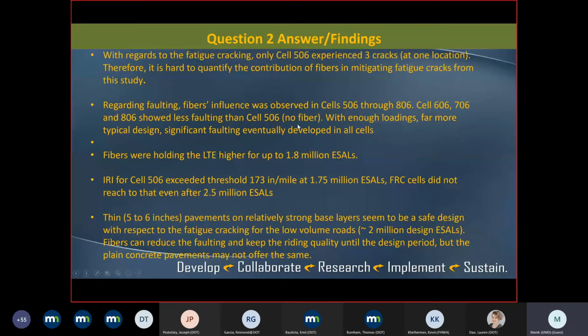So what we learned from this study of cells 506 to 806: with regard to fatigue cracking, only cell 506 experienced 3 cracks at one location. Therefore, it is hard to quantify the contribution of fibers in mitigating fatigue cracks from this study. Regarding faulting, fibers' influence was observed in cells 506 through 806. Cells 606, 706, and 806 showed less faulting than cell 506 with no fiber. With enough loadings, far more than typical design, significant faulting eventually developed in all cells.